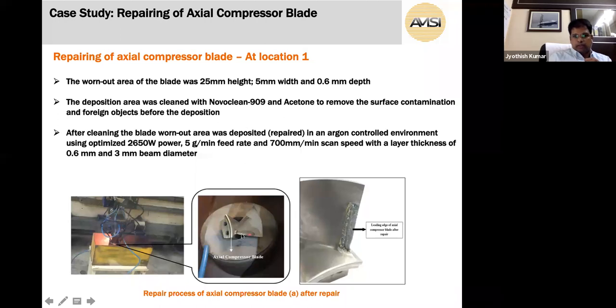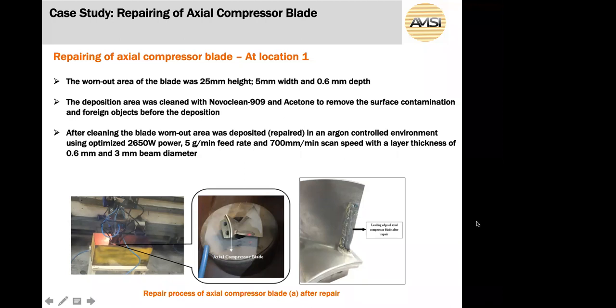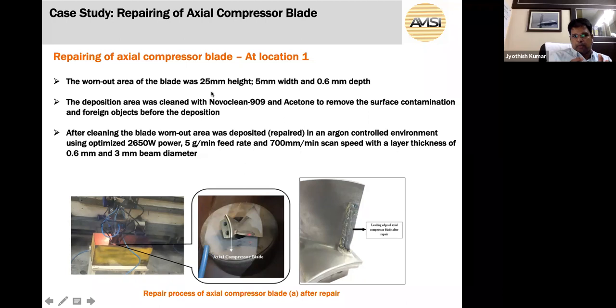Yeah. So we found two locations at the leading edge. Another one is just opposite to the leading edge. So initially we did a lot of preparations before depositing. Any blade or any part which is going for repairing using laser metal deposition, a metal additive process, has to be cleaned with different types of solutions.